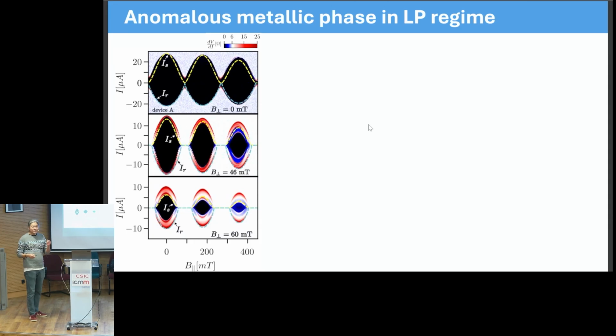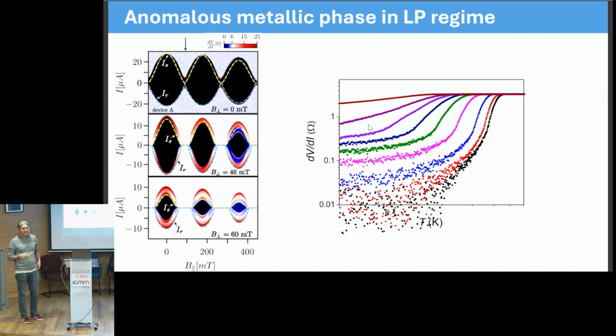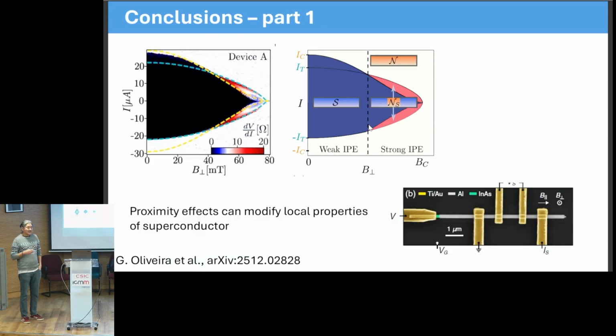So when we can now control and suppress the superconductivity of the wire with magnetic fields, we can generate a weak spot that doesn't dissipate as much heat, and this is what actually leads to this anomalous metallic phase I had mentioned before. This is a mechanism that we have uncovered on this kind of device.